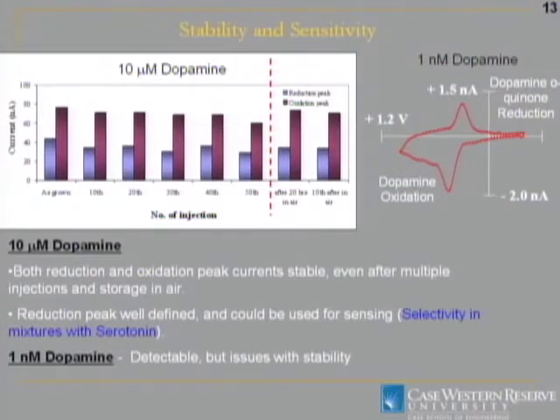But anyway, to point out about the stability of at least the larger concentrations, it's interesting that both the oxidation peak and the reduction peak are stable, which is unusual. Some electrodes don't have the good stability of the reduction peak. That reduction peak becomes an advantage when you look at chemical selectivity.